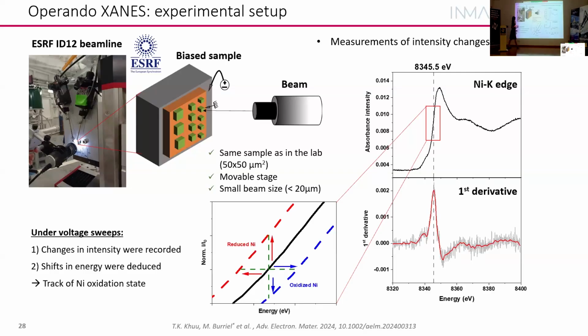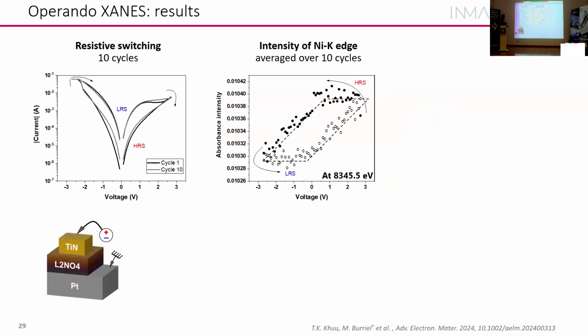So we know that if the edge moves to the right, we will have oxidized the nickel, so the intensity will decrease. And if the intensity at this point increases, it means that we reduce nickel. So it was a way of trying to do switching measurements that worked very well at the end, after lots of trials. So here we have, for example, 10 cycles of these IV samples, and there we're measuring